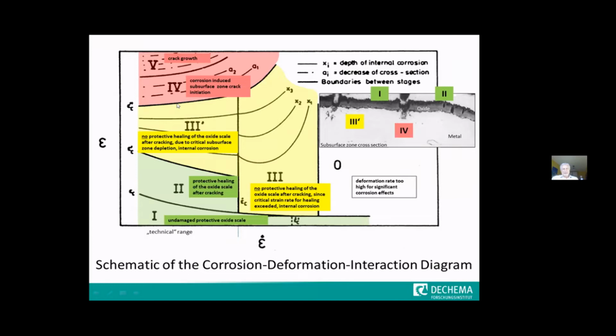And once the internal oxidation along grain boundaries starts, then we can end up in a situation where corrosion-induced subsurface crack initiation can start, as we've seen it in the slide before. And this may move on to a stage where then corrosion-supported or corrosion-assisted crack growth can take place.